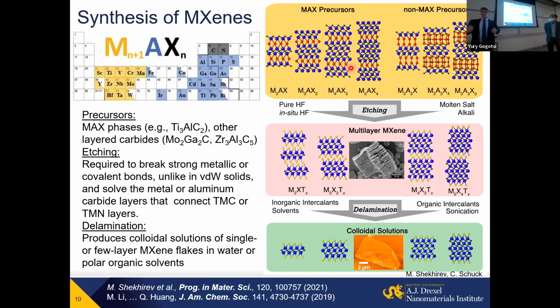So we wrote a proposal to DOE. I invited Professor Michel Barsoum, who was working on MAX phases at Drexel, to join. And we got $1 million for developing MAX phase anodes. Unfortunately, lithium did not know about our DFT calculations and totally refused to go into the structure. Years later, we showed that by making nanoparticles and so on, we can achieve it.